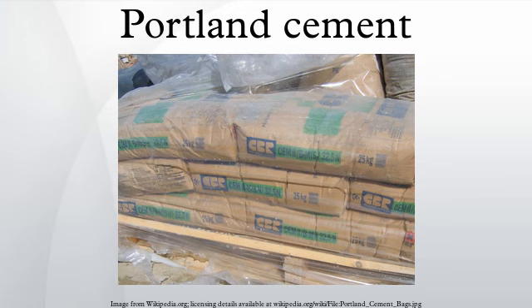The CO2 associated with Portland cement manufacture falls into three categories. Source 1: CO2 derived from decarbonation of limestone. Source 2: CO2 from kiln fuel combustion. Source 3: CO2 produced by vehicles in cement plants and distribution. Source 1 is fairly constant, minimum around 0.47 kg CO2 per kg of cement, maximum 0.54. Typical value around 0.50 worldwide.